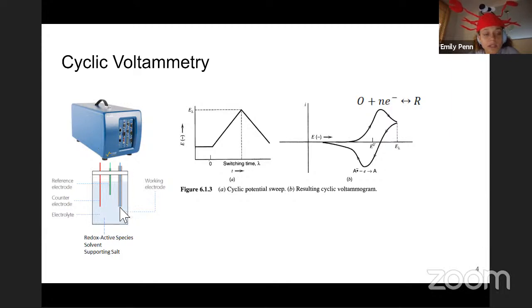We have a working electrode, which in our case is normally a platinum or carbon inlaid disc electrode. So it's a disc of platinum or carbon, and then it's inside of an insulating cylinder. We have a reference electrode. What reference you use is particular to what type of system you're working with. So if you're working with an aqueous system, you might use silver chloride.